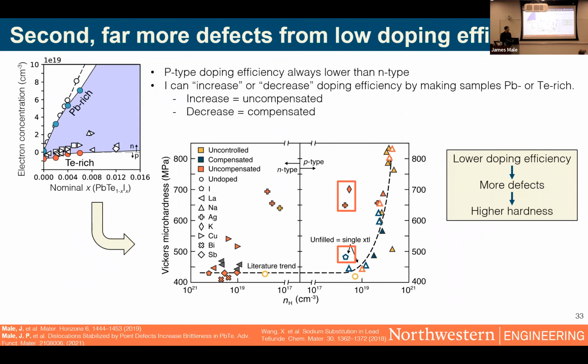The other point I want to bring up is a fundamental difference between N and P-type lead telluride, and that's the doping efficiency. I showed you in the first project here that N-type lead telluride can have a very high doping efficiency, which means there are very few compensating defects. But P-type lead telluride actually never reaches the same doping efficiency.